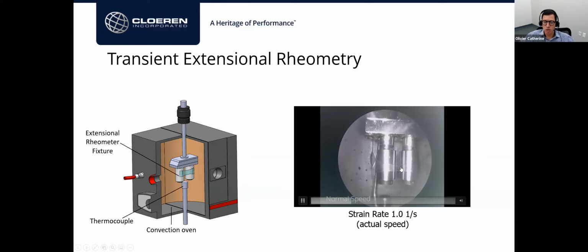We could see what's going on in the oven there, and once the polymer is melted, we started stretching it and measuring torque. As we do that, we are able to convert those values into a transient viscosity over time, and compare that to the Trouton ratio, which is basically the shear viscosity multiplied by 3.